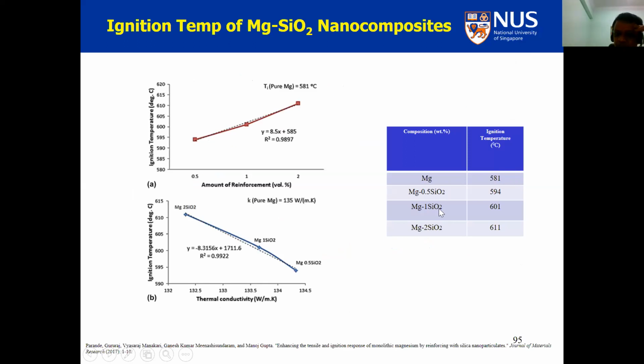If you put nano reinforcement, you can simply improve the ignition temperature to 611. And this graph on the top side says that the amount of reinforcement leads to an increase in the ignition temperature. It also reduces the thermal conductivity of the material, and also the ignition temperature is increased.